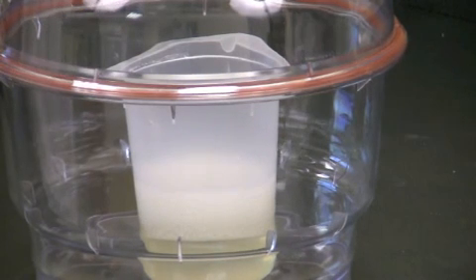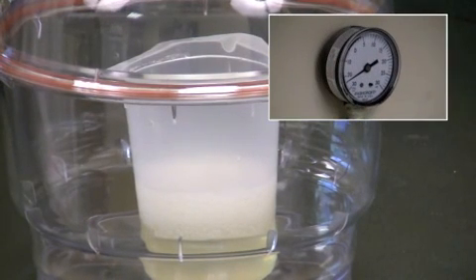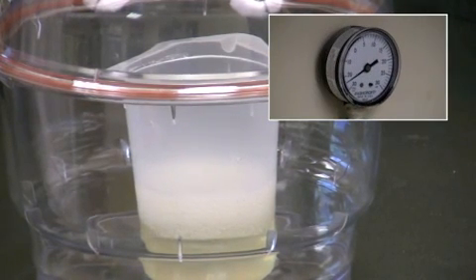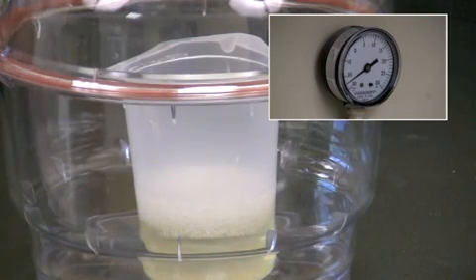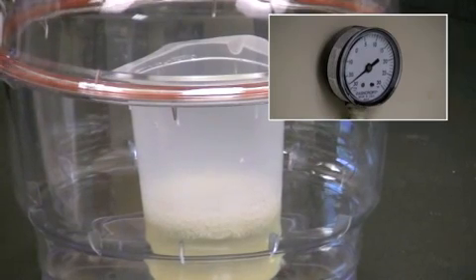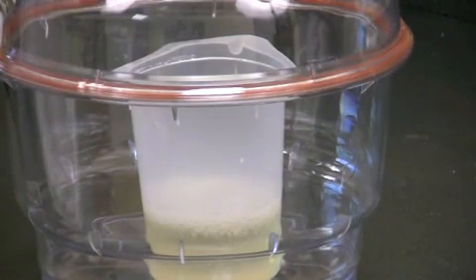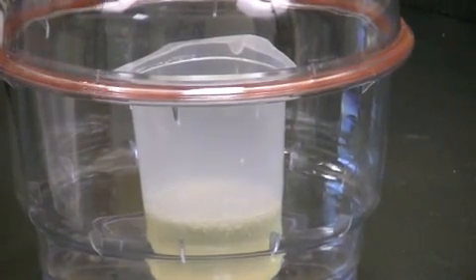Normally, as a rule in the lab, I always have about one-third of the container as liquid and two-thirds for the expansion. It just depends on the polymer. Well, it looks like we've reached the end and the polymer has stretched and it's all starting to settle down now. Just keep on with the vacuuming until it goes clear. And then we'll be ready to pour into our mold.